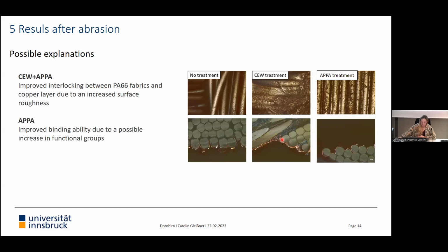We assume that especially for the CEW treatment, there is an improved interlocking between the PA66 fabric and the copper layer due to an increased roughness. The same can also be applied for the plasma treatment. And for the plasma treatment, we have also observed via XPS measurements that new functional groups were formed. This would also improve the binding ability of the fabric to the metal.